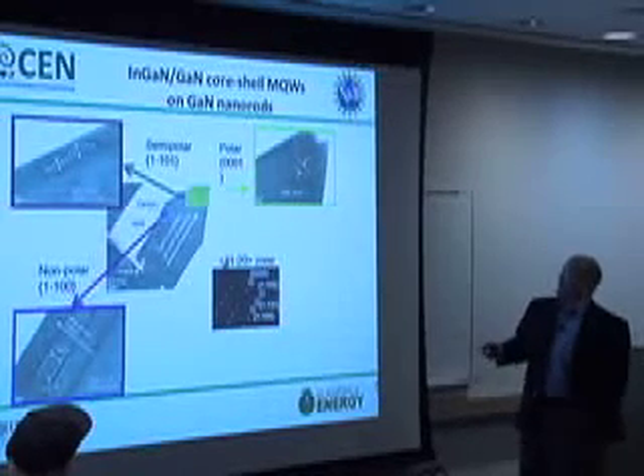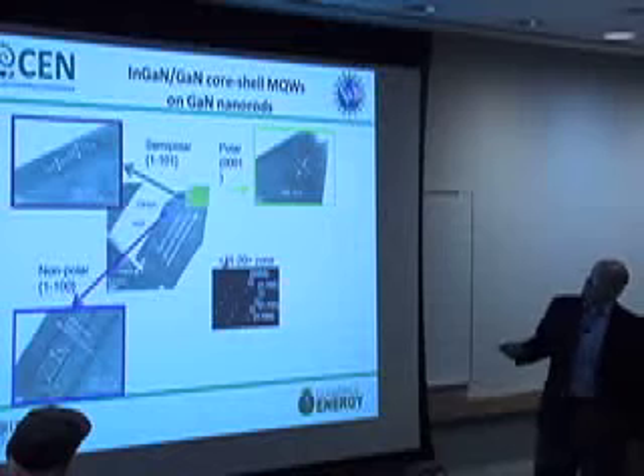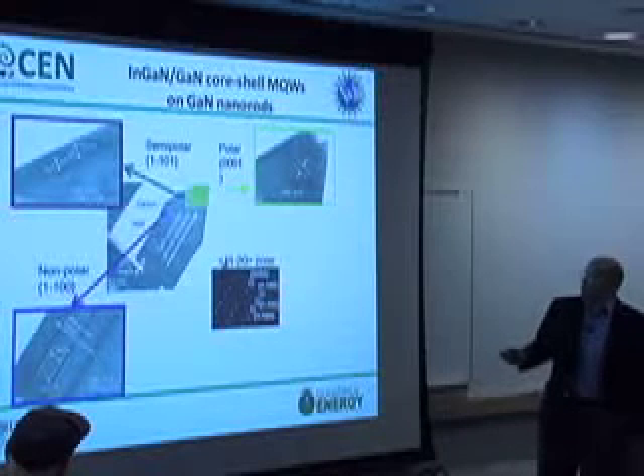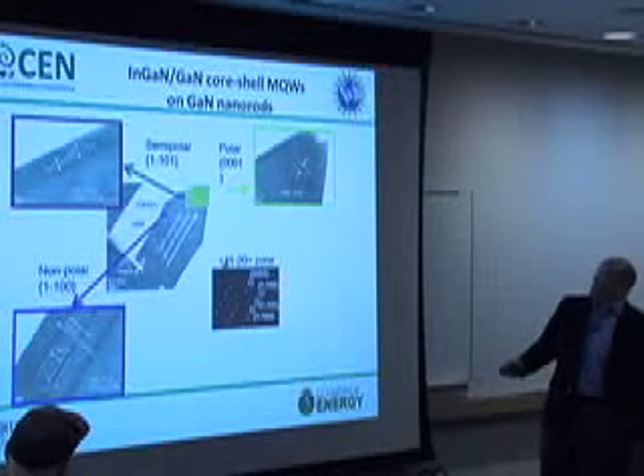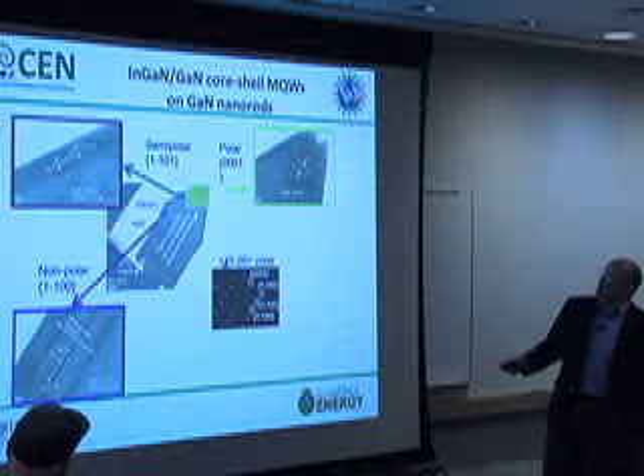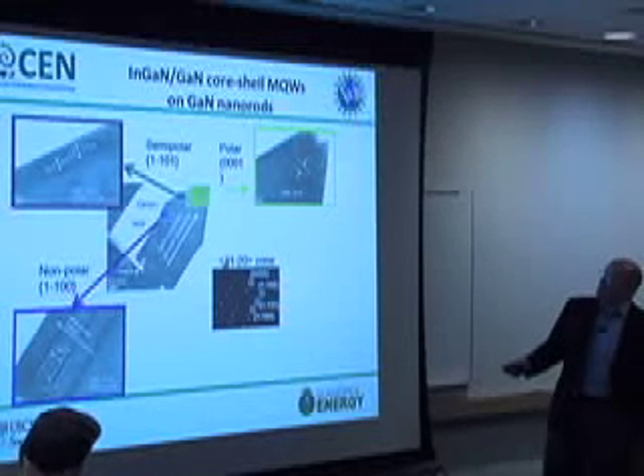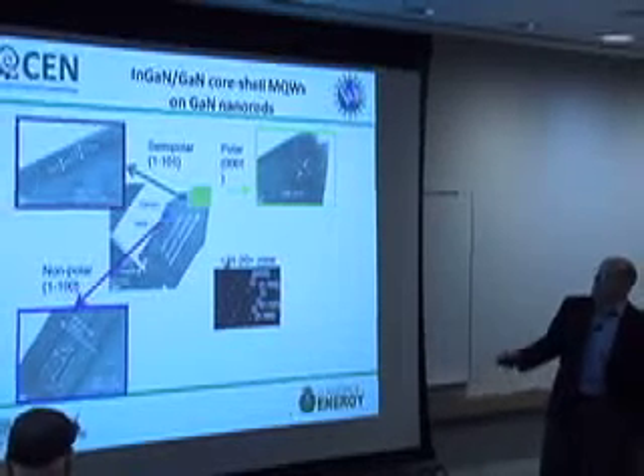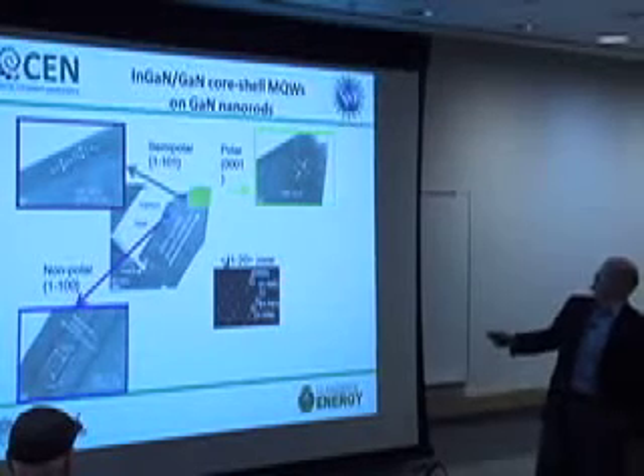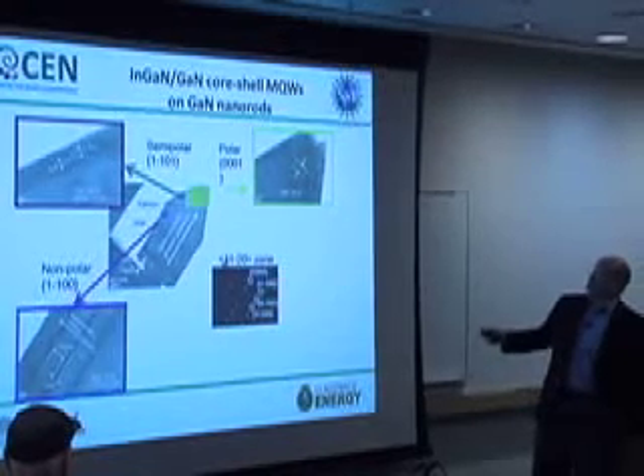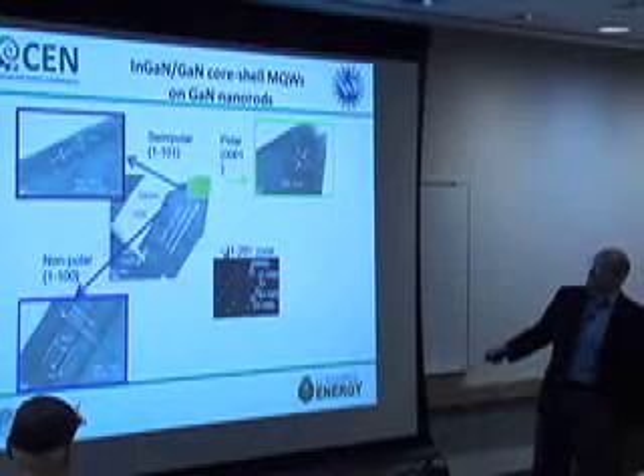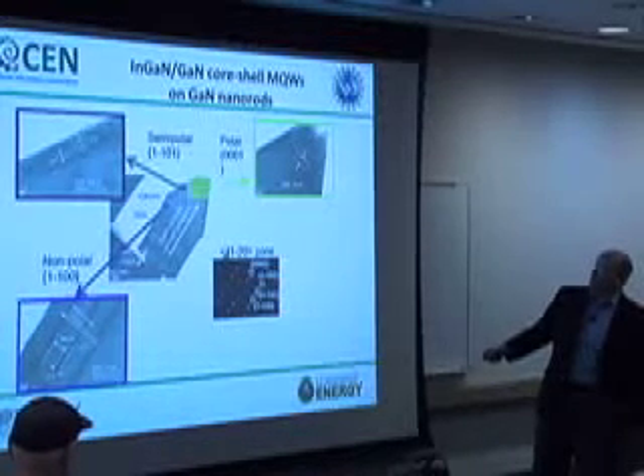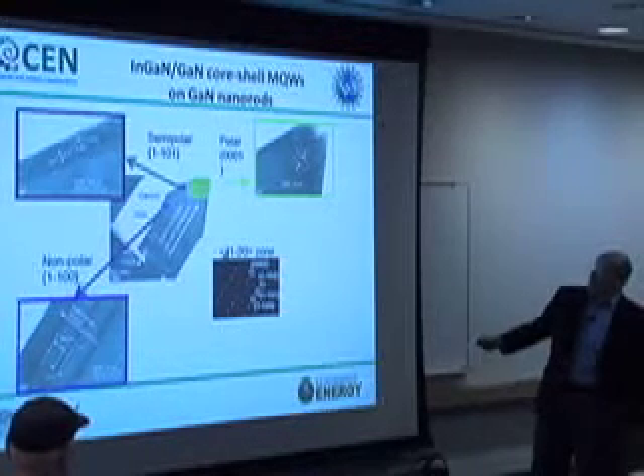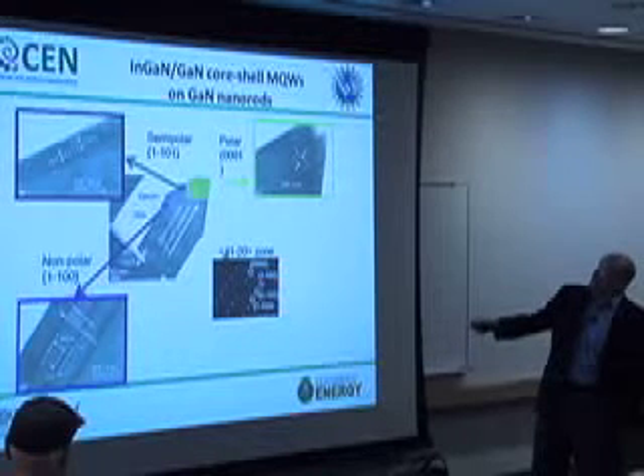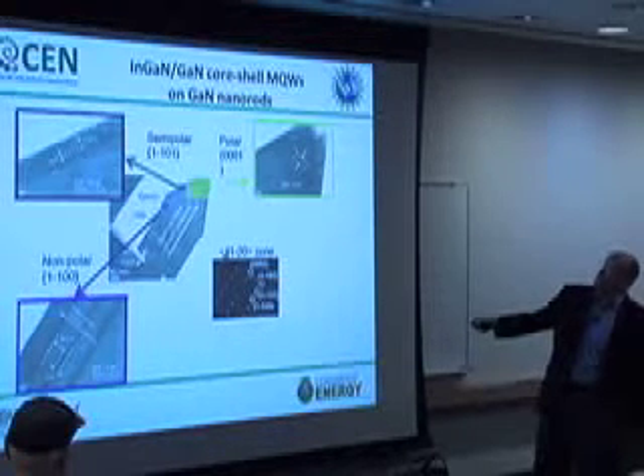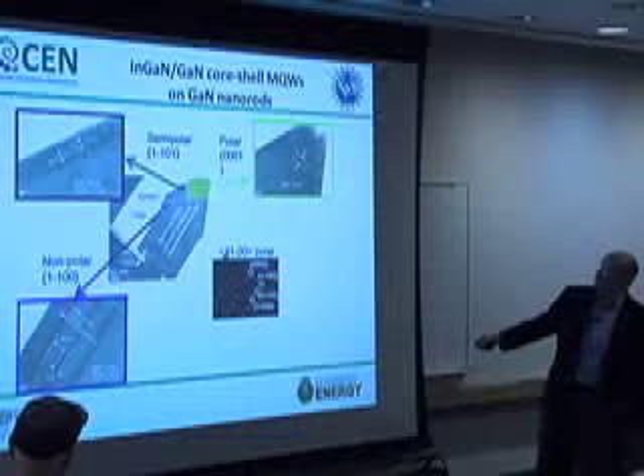Someone would argue that that's not a big deal, but I kind of like it. So, what we decided from this study is that if you grow on the C-plane, the growth rate is about a factor of 2 higher than if you grow here on the M-plane on the side. But the growth over here is exceedingly slow, about a factor of 3 or 4 less than the growth rate over here.